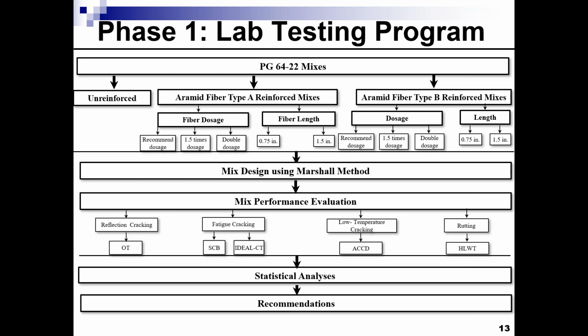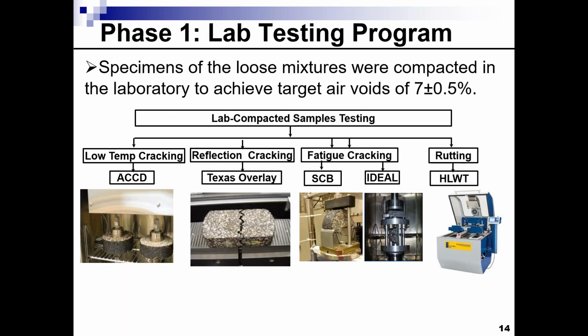But because the additive, or the components of each one, is different, we had to use different dosages. But again, in all cases, the recommended dosage included 2.1 ounce of Aramid fiber per ton of mix, and then 1.5 times that, and then 2 times that dosage. We did the mix design, and then we did the performance evaluation that we discussed in the previous slide. So this is an overview of those tests that we have used.